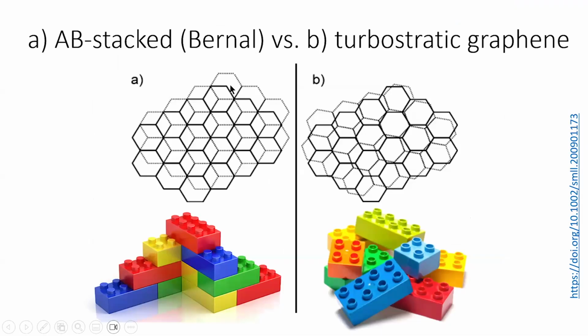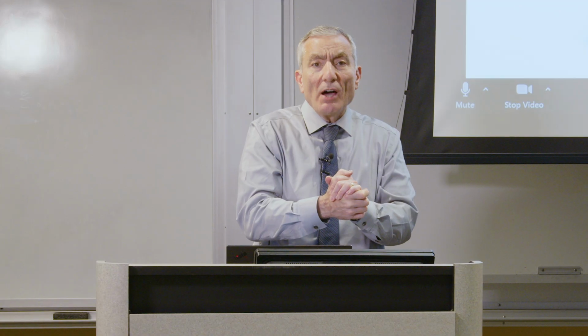AB stacked means that you have the one layer in black and the second layer in dotted lines below it. So you have this perfectly offset, so you have the electron rich edges of this benzenoid ring over the electron deficient portion of the benzenoid ring, because the middle of the benzene ring is low in electron density. The edges are very high in electron density. So you put the low over the high, and they hold together. So they're tough to exfoliate.